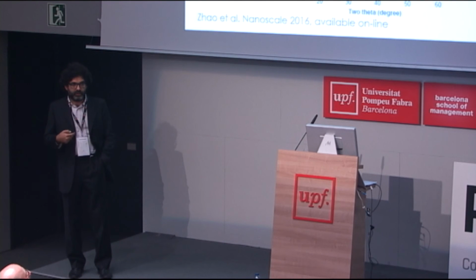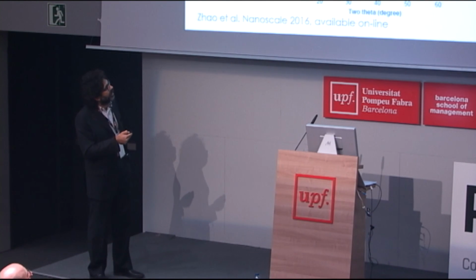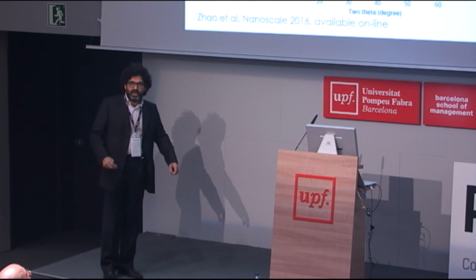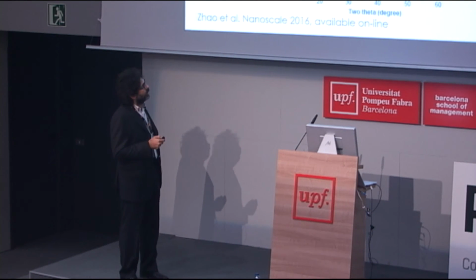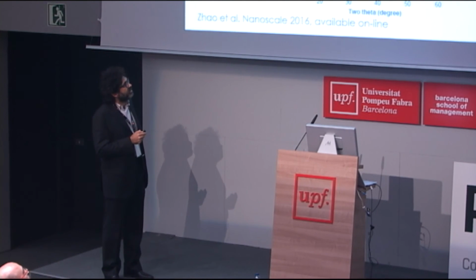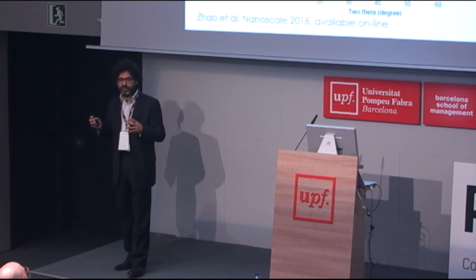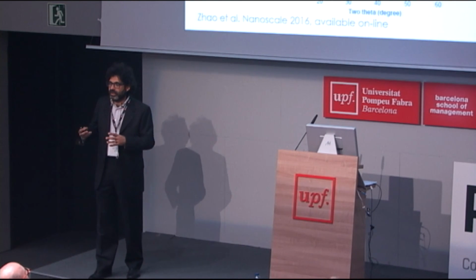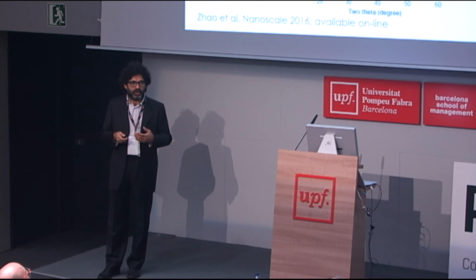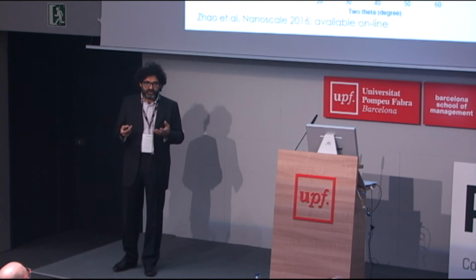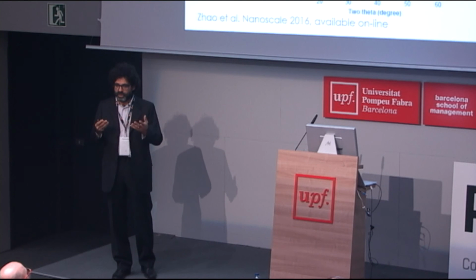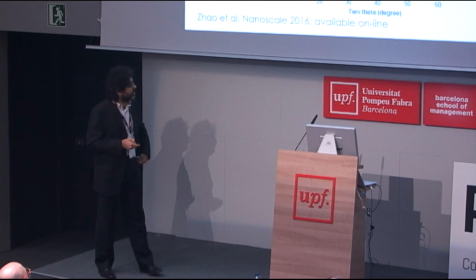We demonstrated that they are not spherical at all. We identified a zinc blende structure surrounding the core, and then a Wurtzite structure growing outside the zinc blende structure. So it's not at all a core-shell structure. Probably since the luminescence comes from the Wurtzite and from the core, this spatial separation of the two regions can affect the ability of the system to keep the two optical properties separated, because there is less communication between electrons from the core and the shell than in a standard core-shell structure.